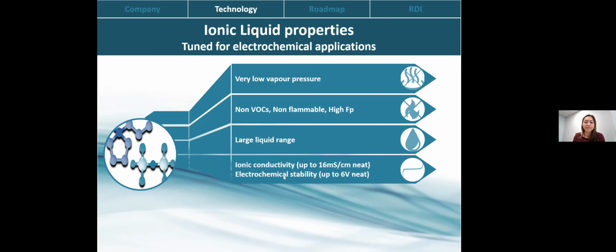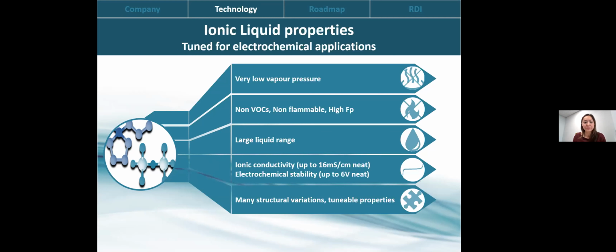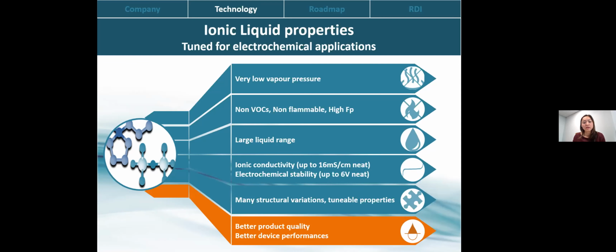Ionic liquids have reasonably good ionic conductivity, up to 16 millisiemens per centimeter. And then they have very good electrochemical stability, up to 6 volts. Of course, here good ionic conductivity is relative. For example, if you have very good conductivity, you might also have a compromise on the electrochemical stability. So a lot of pairing is to be done. We have many structural variations that give us the ability to tune the properties, and also we can produce very good high quality products, which gives good device performances.